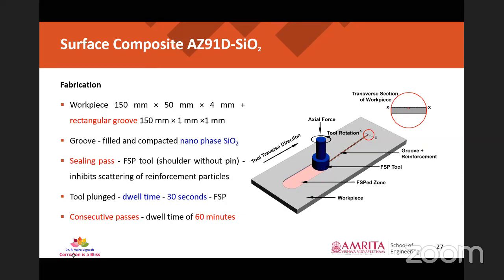So we have taken a workpiece of dimension 150 by 50 by 4 mm, and we have made a rectangular groove of 150 by 1 by 1 mm on the surface exactly at the middle, and that groove was filled with nanophase silica particles, and it was compacted using mechanical pressing techniques. Then we have done a sealing pass. So in the sealing pass, what we do is we take an FSP tool with a shoulder, without a pin. Then we just insert it over the surface so that it will inhibit the scattering of reinforcement particles when we exactly do the friction stir processing.